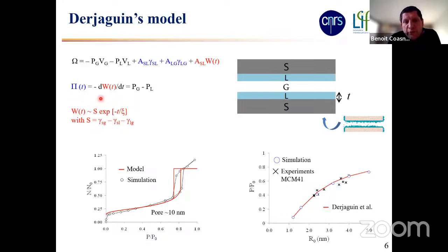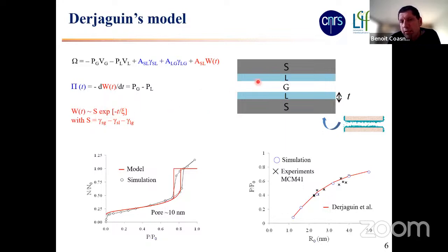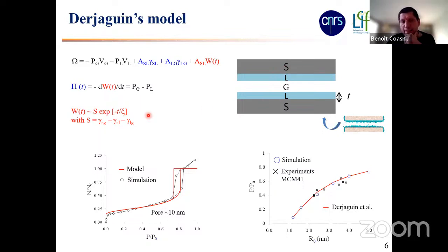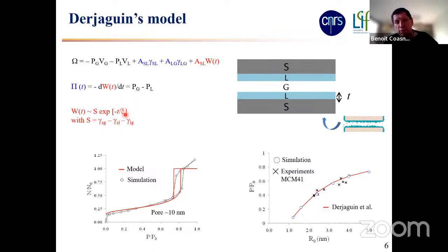You can use different shapes for this surface potential, but a simple one is an exponentially decaying function. T is the film thickness, and as the film thickness grows, molecules get adsorbed at larger distances from the solid, so the potential decays with distance. Xi is basically the range of these intermolecular forces — typically of the order of angstroms or nanometers.